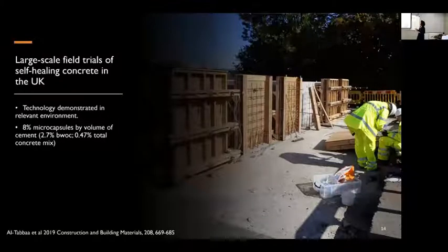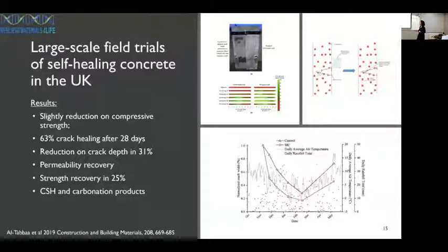One interesting thing to point out here is the sheer volume for producing that, which is quite a lot larger compared with the lab tests that we produced before. And what we see are results that are similar-ish to the results that we observed in the lab: a slight reduction in compressive strength, 63% of crack healing after 28 days, the reduction in crack depth,